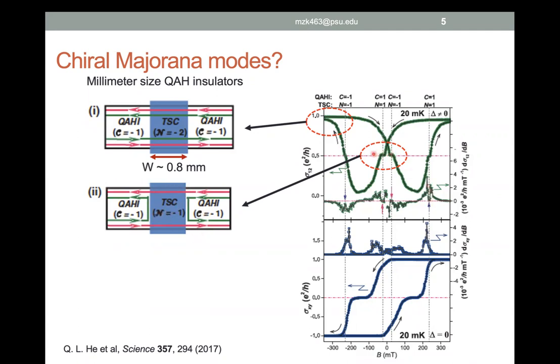half quantized value. I note here that if this picture is true, this value of half quantized conductance would not depend on the number of superconductor strips that you put here. If you increase the superconducting strips from 1 to 2 to 3 to 4, it does not impact the quantization. You should always see a half quantized conductance. Anyway, they interpreted this half quantized conductance as evidence for chiral Majorana.